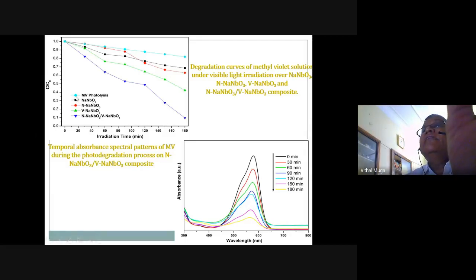Now this is photolysis of methyl violet dye. It has decomposed about 10% only, by photolysis. Pure NaNbO3, you take it, its activity is very less. It could decompose only up to 20%. N-doped NaNbO3, you take it. This is also not much from the parent compound. V-doped, you take it, slightly better, but it is still not much. But when you prepare a composite of these two, then you see that more than 90% decomposed.